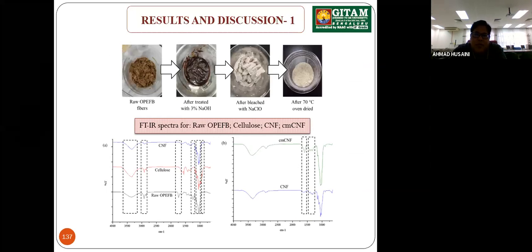Okay, so result one shows that the raw OPEFB fiber, after bleaching and pre-treatment using sodium hydroxide and sodium hypochlorite, turned in color from brown to a grayish light color. The FTIR showed that the peaks at 1,700 and 1,240, which represent hemicellulose and lignin, disappeared after isolation of the cellulose nanofibril. During introduction of the carboxymethyl group, a peak was observed at approximately 1,600, which indicates the introduction of the carboxymethylated group. Next.